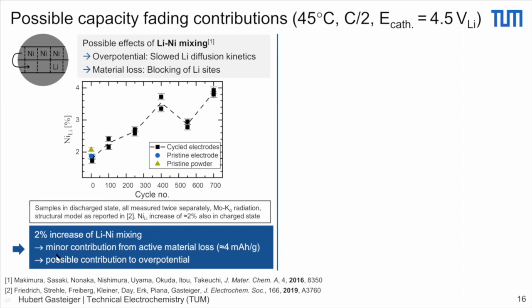So if you look at it, what would this mean in terms of active material loss, where you are essentially blocking lithium sites, that would be very little, about 4 milliamp hours per gram. But of course, what we cannot determine from here is what kind of overpotential this would induce. So it is a possible, but most likely a minor degradation mechanism.